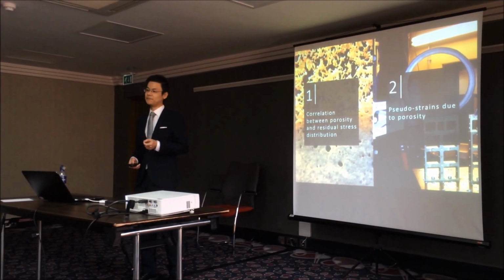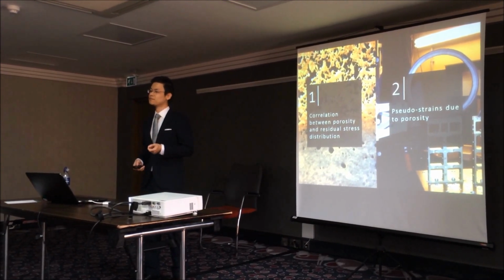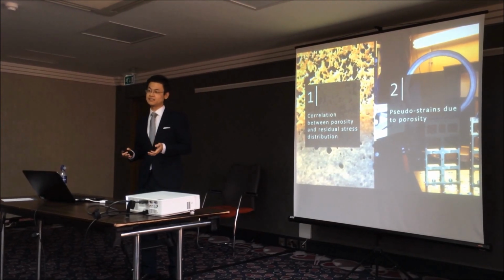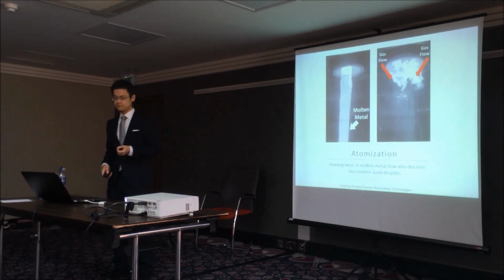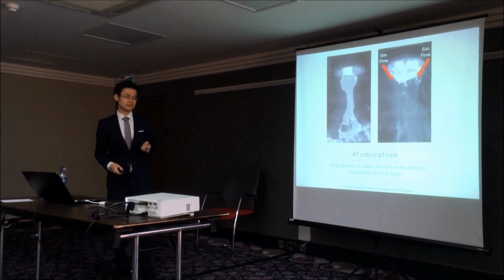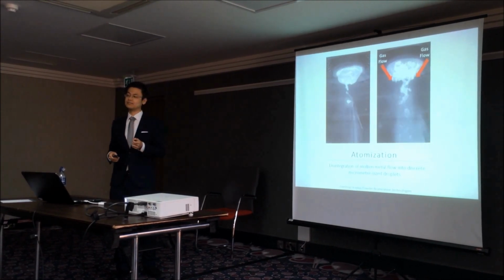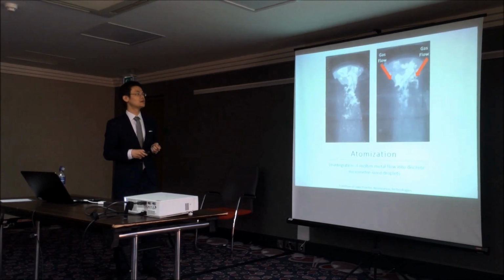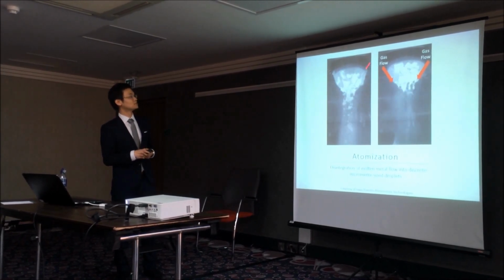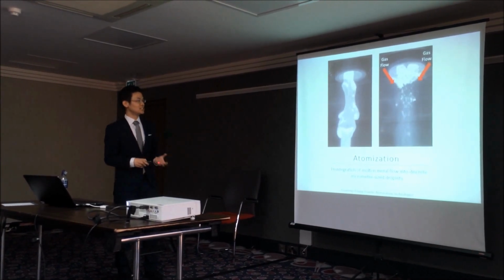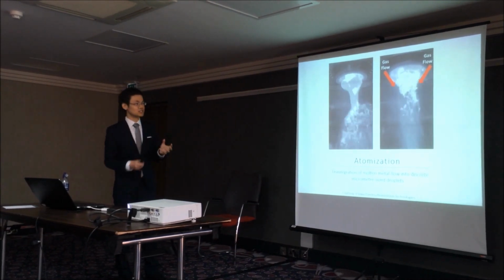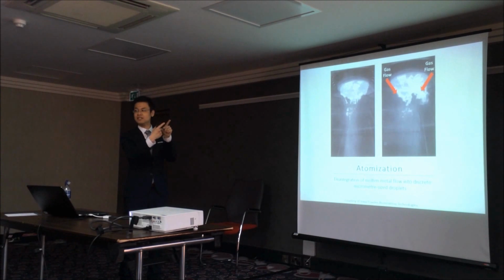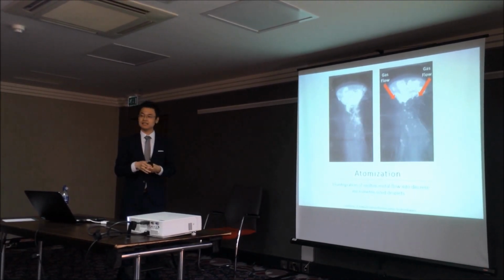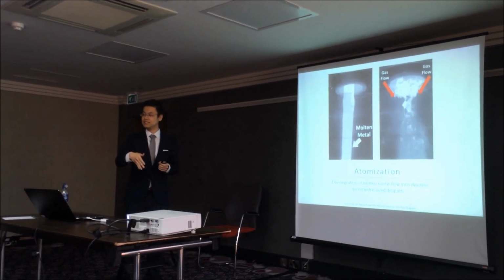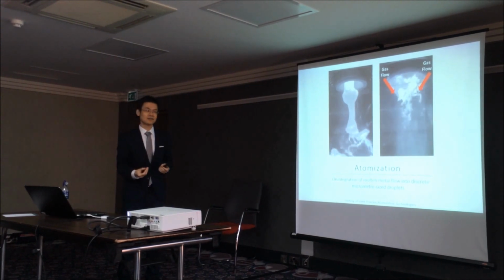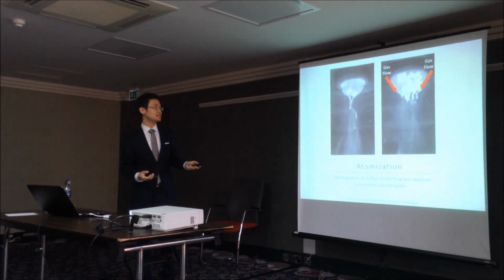So I will now introduce the spray forming technique by showing a video of how the metal spray is created in this casting process, and that is through atomization. So the liquid metal flow is disintegrated when it is subjected to high velocity and high pressure gas flow that is channeled into the spray chamber from the nozzles surrounding the molten metal flow. Now, the initial upwards motion of the molten metal is due to a low pressure and recirculating gas region. And in this region as well, we can see that the liquid metal flow is torn into ligaments, which then subsequently form the tiny droplets. And these droplets are subjected to high cooling rates in this gas flow field.